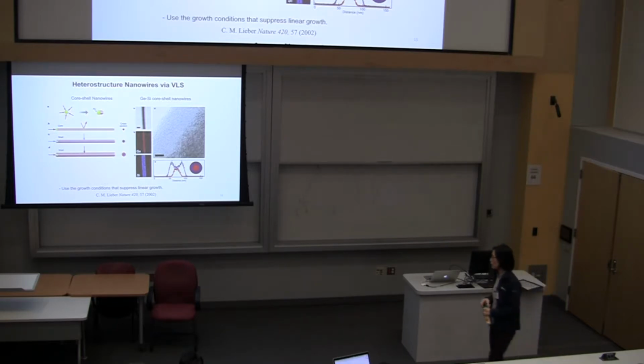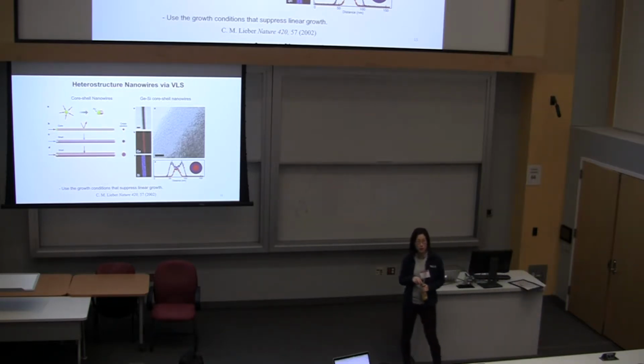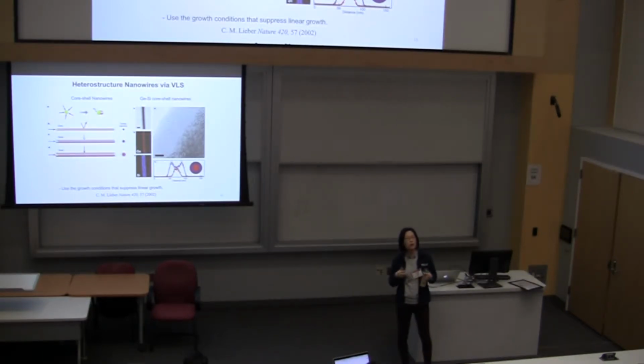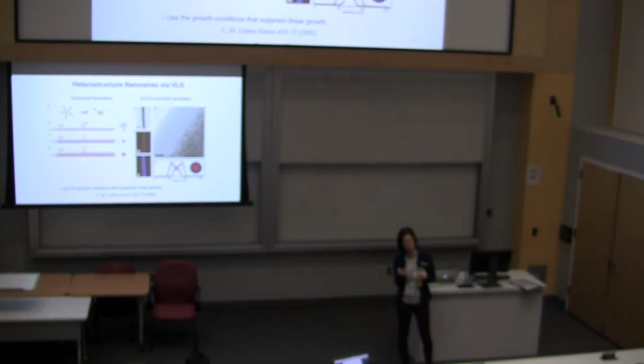PN junctions, people try to make PN junction solar cells using nanowires. You can then decouple the absorption length for the light from the recombination length of the electron hole pairs. So then people did this core P, let's say, shell and PN junctions, so that radially the length is pretty small at the nanoscale, so you don't recombine the electron hole pairs. But the wires are pretty long, so that the light absorption happens along the length, and you're going to put it in a periodic array of the nanowires so that you also set up some photonic modes, which helps to enhance the light absorption.